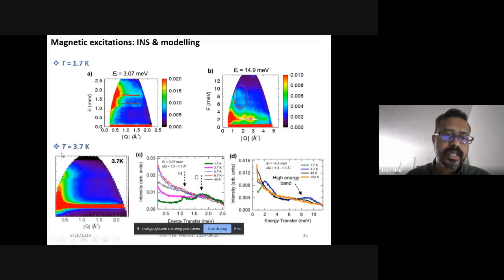Plus, if you increase to a slightly higher temperature, 3.7 Kelvin, remember that this temperature is between the temperatures where the helical and the collinear orders develop. So you should not see one of them. And in fact, we don't. At 3.7 Kelvin, we don't see the helical order, because that order develops only below that temperature. So it's not yet there.